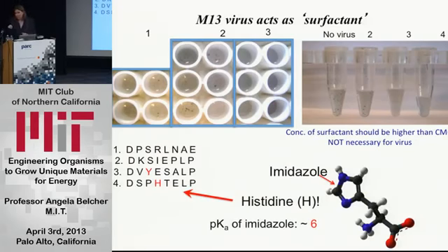As the women in my 303-4 class will remember, the answer is almost always histidine on an exam. Because histidine is a very natural, very amazing amino acid. It's an amino acid that can be charged or uncharged at physiological pH. And it was actually the magic amino acid sequence that allowed us to do two things simultaneously. One, it was good at binding CNTs for pi interaction, but it also could act as a switch that allowed us to change the pH, bind a carbon nanotube, make it soluble, and then change the pH and grow titania nanoparticles simultaneously and grow hybrid materials.